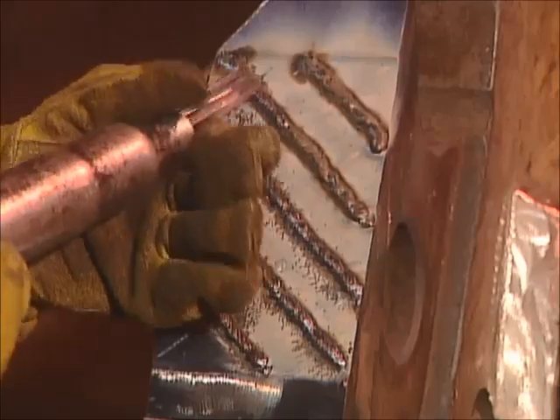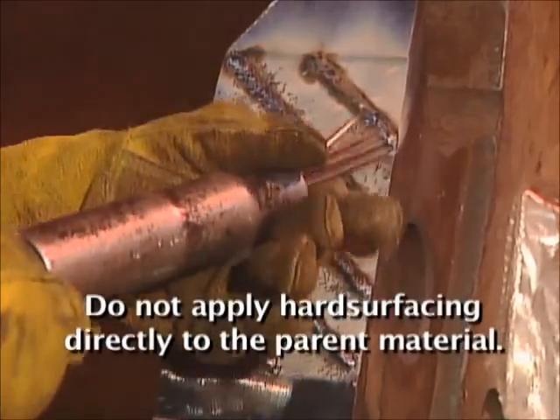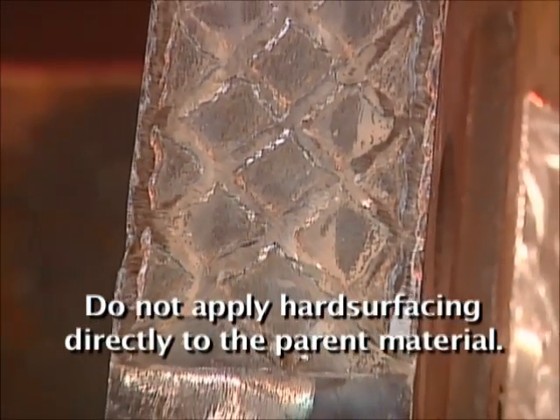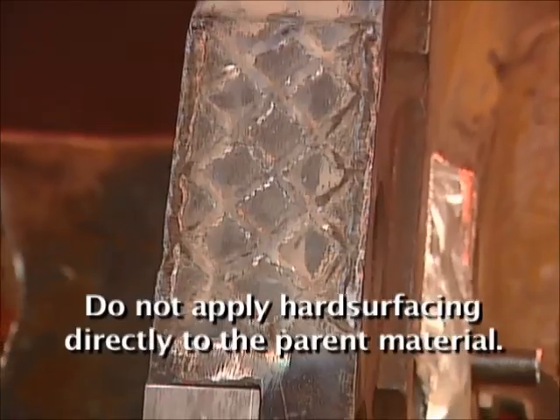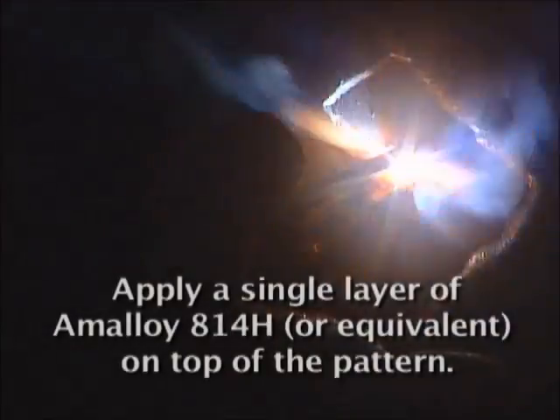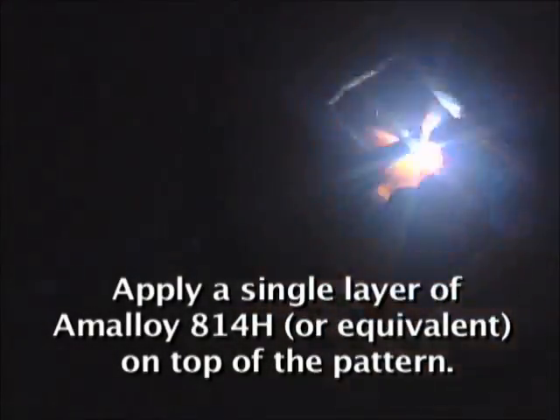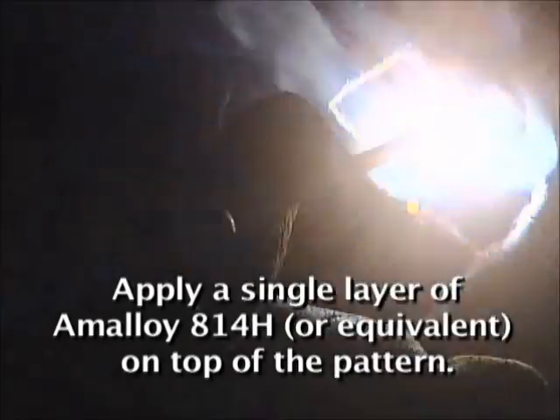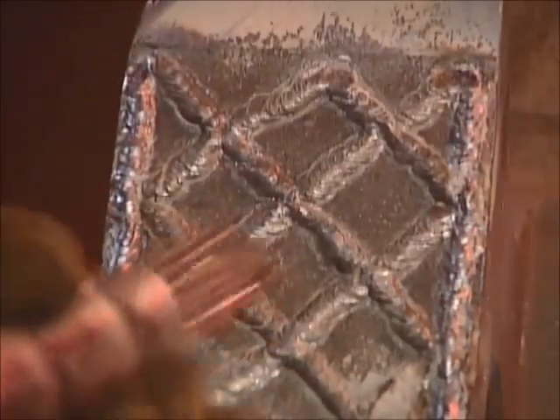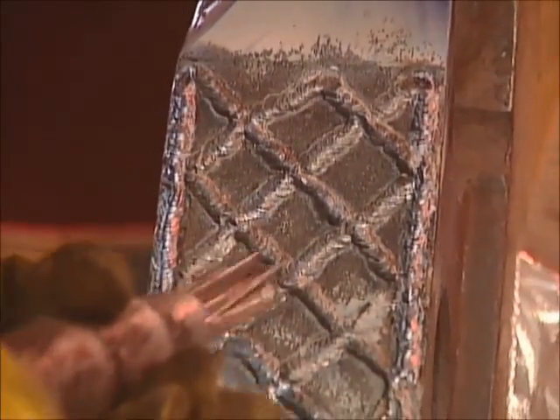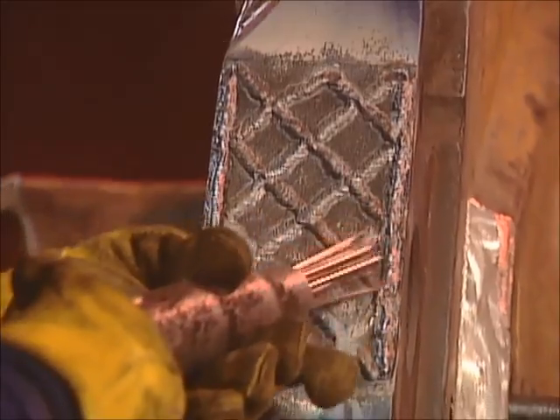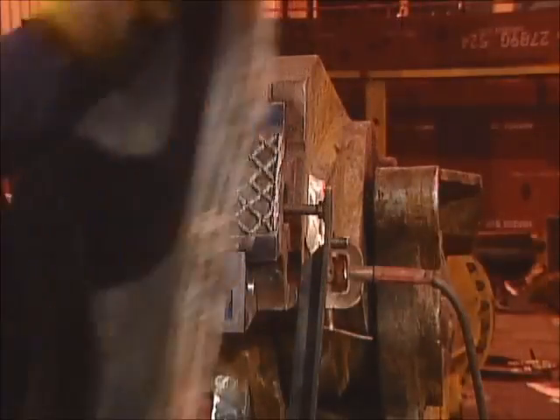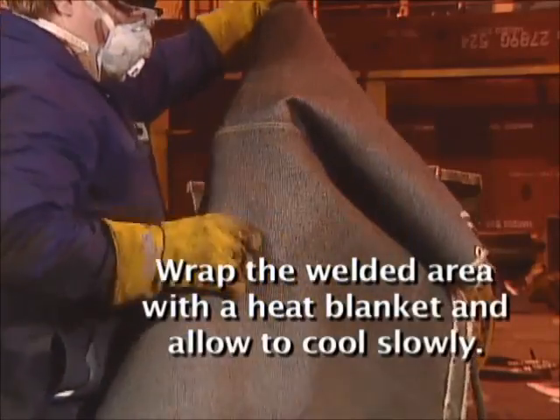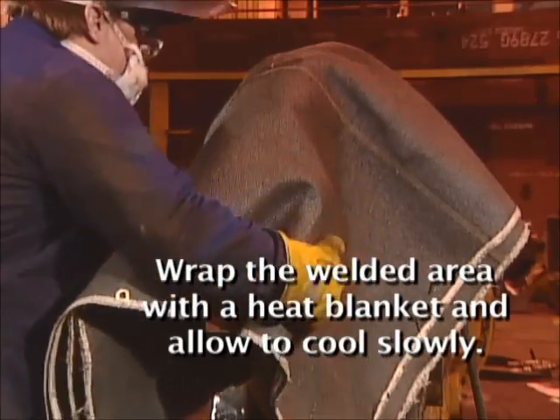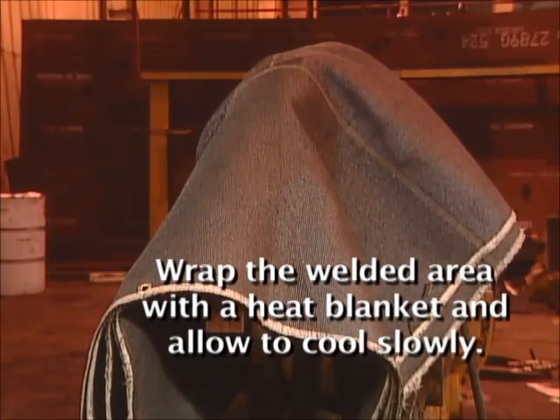Again, this serves as an underlayment for the hard surface beads. Do not apply hard surface directly to the parent material. Apply a bead of Amalloy 814H or equivalent hard surfacing welding rod on top of the pattern. It is important to use an air-operated slag peener on each pass to relieve weld stress. When welding is complete, wrap the welded areas in heat blankets and allow to cool slowly to the ambient temperature before returning the shear to service.